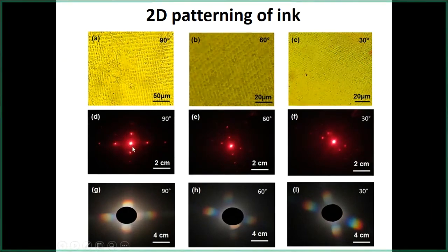The diffraction pattern that comes from them shows the true image. These are some rhombus type structures. And as you can see, we have done multiple exposures. For this exposure, we rotated the sample by 90 degrees. Over here, we rotated by 60 degrees, and over here, we rotated by 30 degrees. It changes the shape of the diffraction pattern these gratings produce.